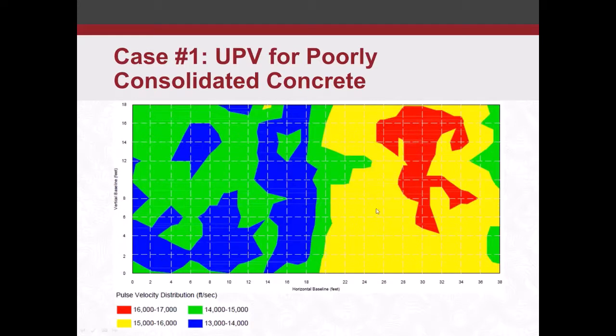But anyway, here are our wave velocities: mostly yellows and reds, maybe some greens. And then here on the left, we've got mostly blues and greens. These were actually two different placements. And when we did compressive strength testing on these cylinders, we obviously got two different strengths. The one on the left was about 5,000 psi. The one on the right was about 6,500 psi. So the higher the strength of the concrete, typically the higher the wave velocity as well. So this does a pretty good job highlighting the difference in wave velocity and how it compares to compressive strength.